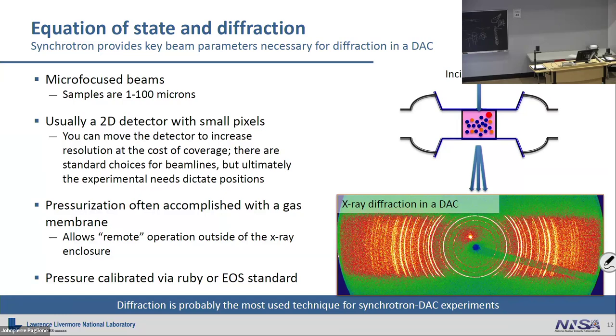This is a picture of what diffraction looks like in one of our DACs. You can see we have rings, so this one we actually had good powder. But you can see as you go out, there's kind of this rectangle. One of the things that we do with a lot of the things that we work on that are metals and we think are powders is, because we want to go to high pressure, we don't keep a symmetric hole in the backing plate that Adam showed this morning. We make a slot. That gives us more meat to hold the diamond. So our cells generally go to higher pressures than if we had just a conical hole. But we sacrifice having no data out here. So there's trades, choices, if you will, on how you want to work your experiment.